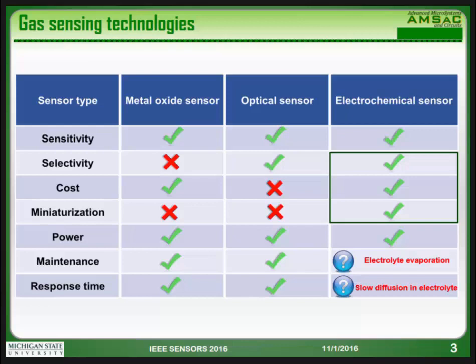But the electrochemical sensor has its intrinsic drawbacks, which is the maintenance. When we use the electrochemical sensor, we need an electrolyte, and the liquid electrolyte easily evaporates, so we need frequent maintenance. The other thing is the response time: the gas needs to diffuse through the electrolyte, and the diffusion coefficient is very low, so it will take a long time.